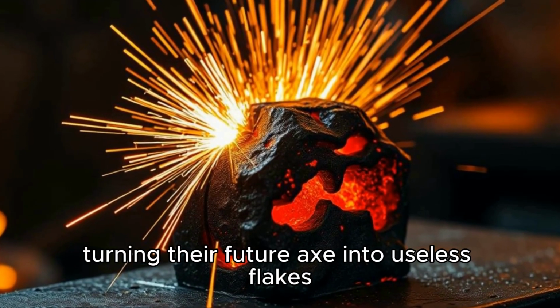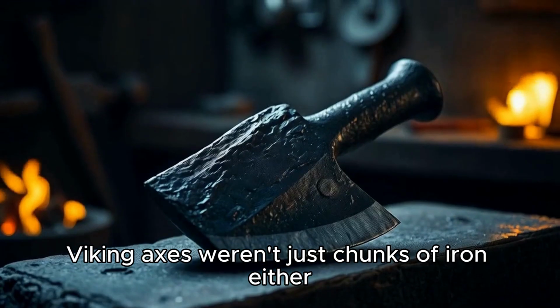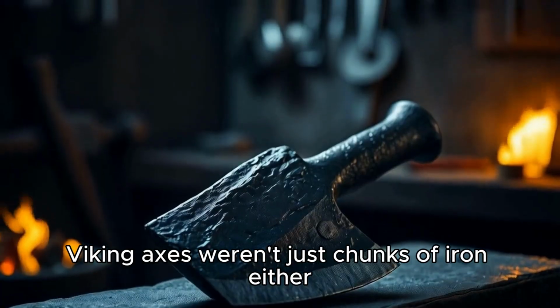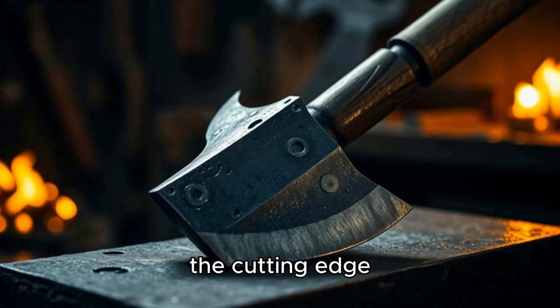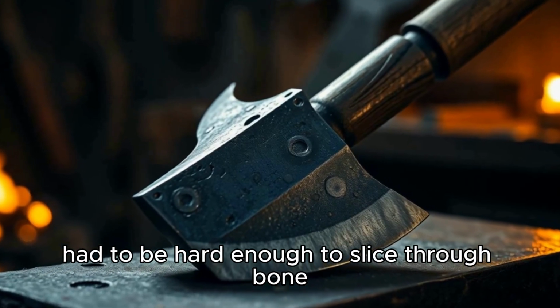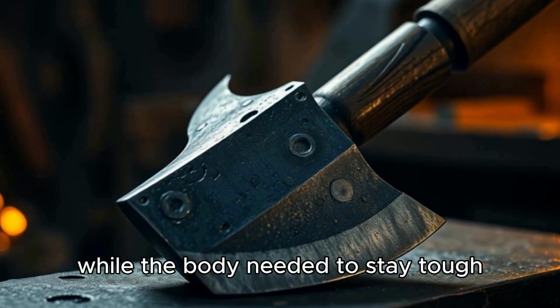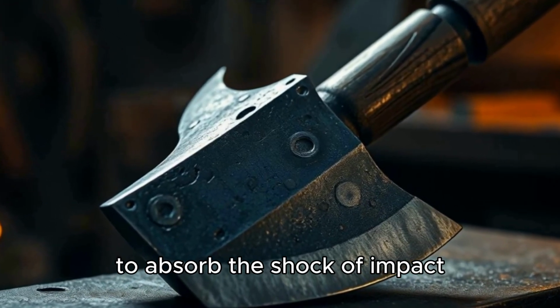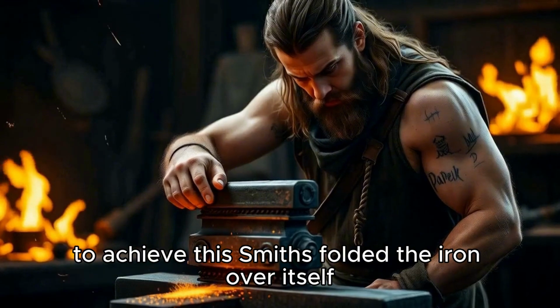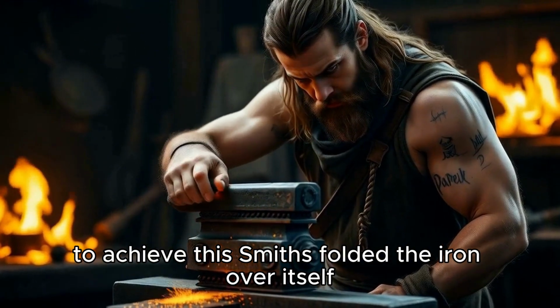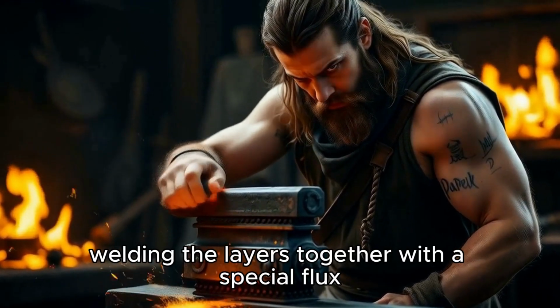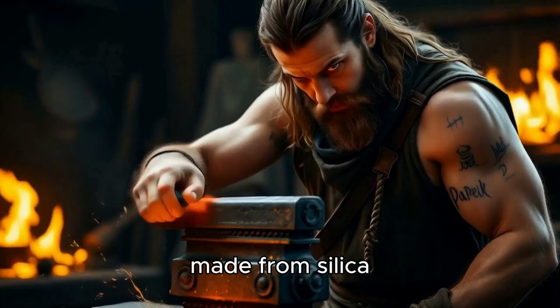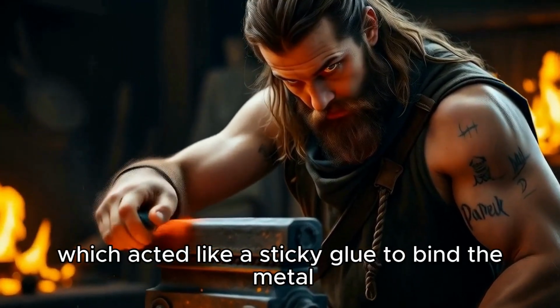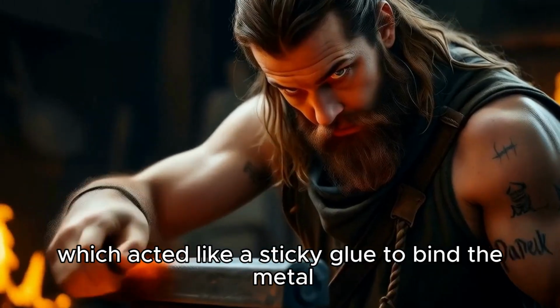Viking axes weren't just chunks of iron either. The cutting edge had to be hard enough to slice through bone, while the body needed to stay tough to absorb the shock of impact. To achieve this, smiths folded the iron over itself, welding the layers together with a special flux made from silica, which acted like a sticky glue to bind the metal.